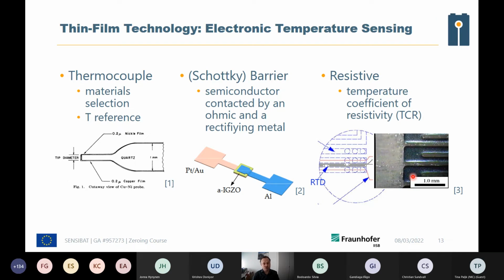There's a range of alternative materials. For example, in this first instance, we investigated a few years ago, which was purely printed. There we used a polymeric material filled with conductive particles, and upon heating, the polymer expanded and particles successively lost contact, so that the resistivity was steadily increasing upon heating of the material. However, as the basic principle of this application is a mechanical expansion and then shrinking again, this has some latency and is also prone to hysteresis effects and some aging that cannot be neglected. We did not follow this way, or do not follow it nowadays anymore.